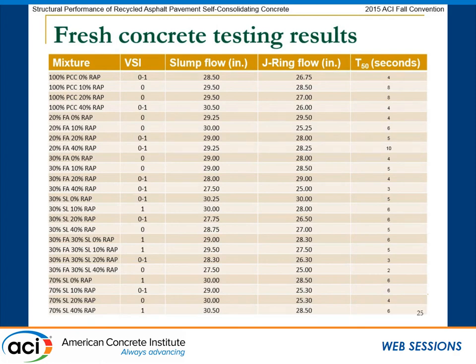When the fly ash was introduced, you can see that you also have a higher slump flow than the control mix. In general, the slump flow was really good. When you look at the J-ring results, you may be interested in the difference between the slump flow and the J-ring results. For most of the mixes, the difference between the slump flow diameter and the J-ring flow diameter was smaller than 2 inches. There are a few that did not meet this criterion, but for most of them the difference is smaller than 2 inches, and that shows that there is not much blocking.